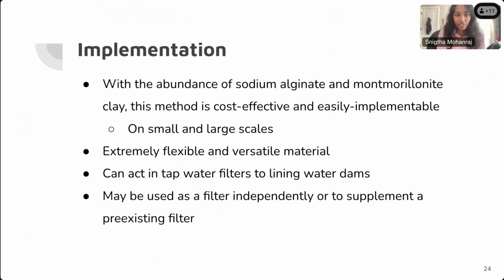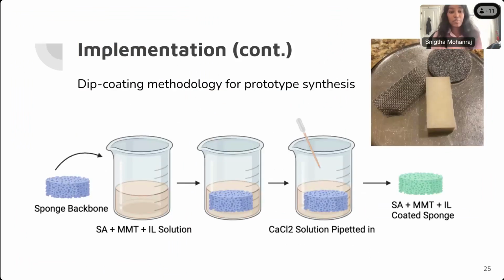so it can be used in a variety of different scenarios. So I'm currently working on a dip coating methodology for synthesizing the prototype, which is noted for being able to provide more stability to the compound I'm using. So instead of a flimsy gel polymer, actually using a sponge or metal mesh backbone to provide more stability. And in this application, I'm specifically working on using a melamine sponge, soaking it in the solution, and then adding the calcium chloride to create a coated sponge in the end. And that top photo shows the melamine sponge, but also metal meshes that can be used in replacement.